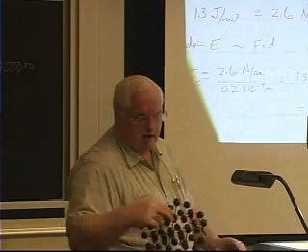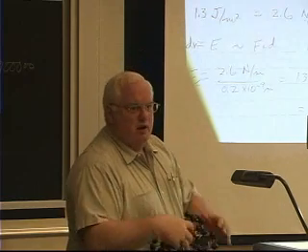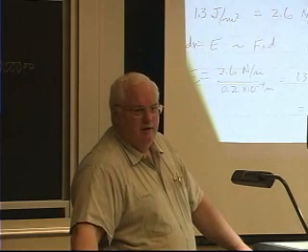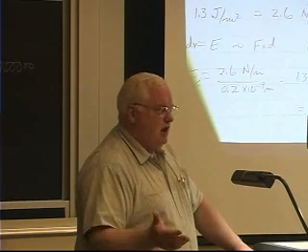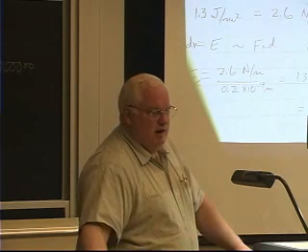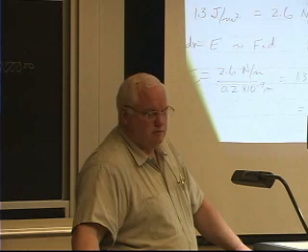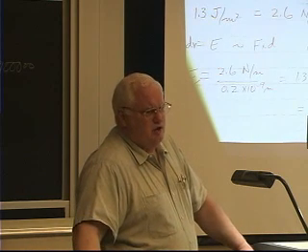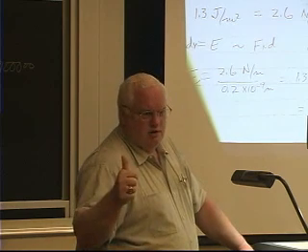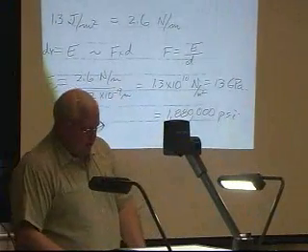A carbon nanotube has this kind of hexagonal structure. If you're missing one atom, you've got a defect there. And all of a sudden, the strength may go down by a factor of 2. Okay? So rather than 2 million, you've got 1 million. If you have a bigger defect, it goes down to 300,000. So you're going to buy carbon nanotubes, and you could actually take a piece of aircraft quality steel and get 300,000 psi. Not KSI, 300,000 psi. Okay, so the carbon nanotube business, they say is going to be the structural material of the future, they've forgotten about cost and they've forgotten about defects in the material. And in fact, we know that defects control the strength of the material. We learned that with the Liberty ships.